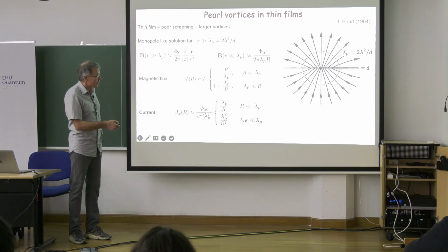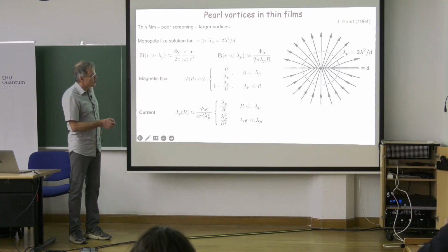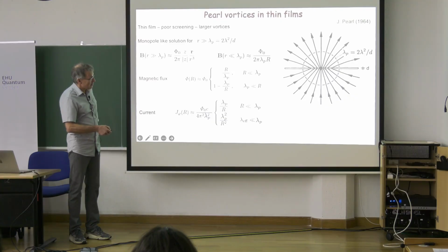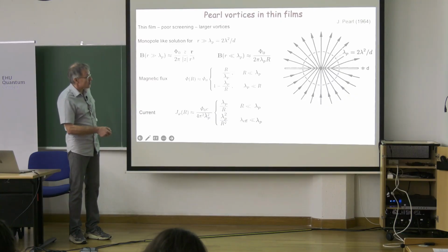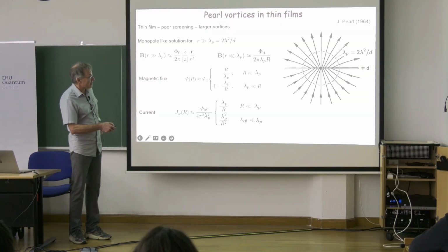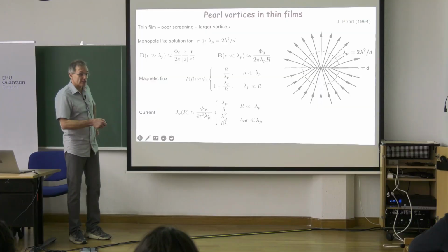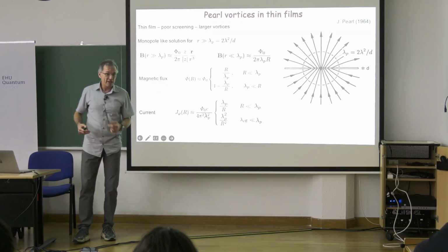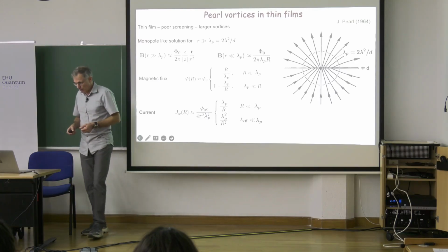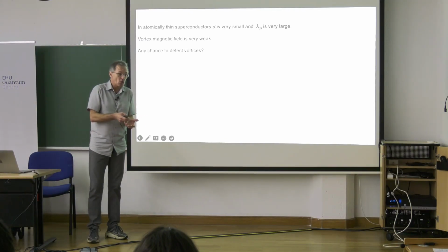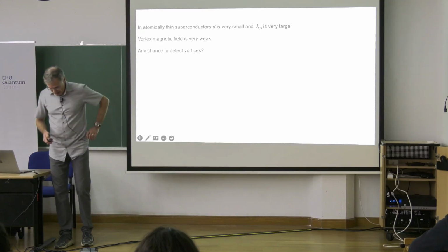At distances much larger than this Pearl length, the Pearl vortex looks like a magnetic monopole. In the upper space, it's a monopole with field going up. In the lower space, it is like a magnetic monopole with fields going inside. The total flux quantum is realized in an area of the order of this Pearl length. So this Pearl length for atomically thin superconductors would be very large, and this vortex would be pretty challenging to observe with magnetic probes, because the magnetic field it produces is so tiny.